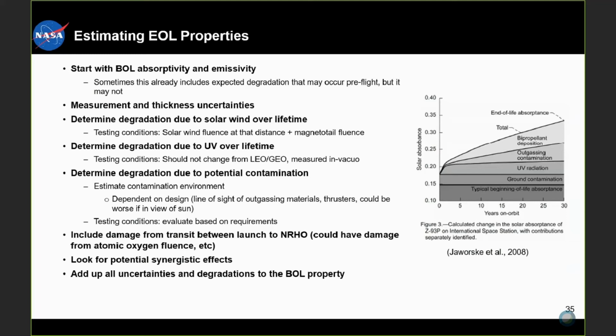So as Brittany and Abby have both identified, one of the primary factors in NRHO is solar wind over the lifetime of the mission. So what you'll do is you can do some testing to determine what the degradation is expected for solar wind. So you'll get some fluence values and some energy values from your environments team, and you'll test your materials according to those values. And then you'll get a delta for your emissivity and a delta for your absorptivity. And then you'll do that for each of the different factors.